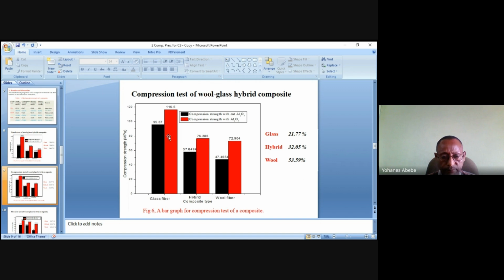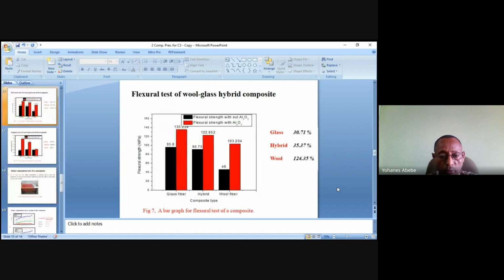The glass fiber, the hybrid composite, and the wool fiber, the data you can collect from this bar graph. So the improvement as a result of alumina nano enhancement is, for the glass, 21.77%, for the wool fiber, 55%, and that of the hybrid composite is 32% improvement in the compression strength of the composites.